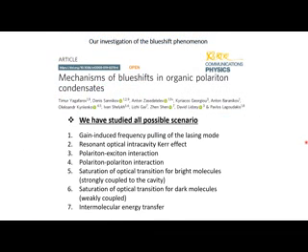And in our study, I believe we figured out what's going on because we studied all possible scenarios that could contribute to a change of the energy in the polariton system, not only blueshift, just all possible changes of the energy. Of course, we considered polariton-exciton interaction, polariton-polariton interaction. We considered saturation of optical transition for those molecules which are strongly coupled to the microcavity.